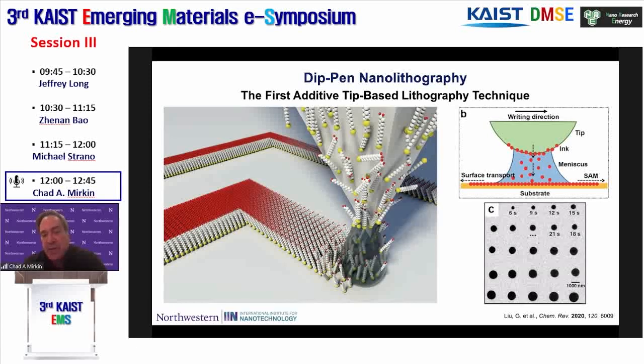As a chemist, when I looked at this, I thought, this is interesting, but it'd be a heck of a lot more interesting and functional if we could learn how to use it to control chemistry. And we could think of that water effectively as a solvent. And if we coated the tip with molecules that could chemically react with the surface, we could create a driving force to move molecules from the tip over or through the water to the underlying substrate to form stable monolayers. And that was the birth of dip-pen.